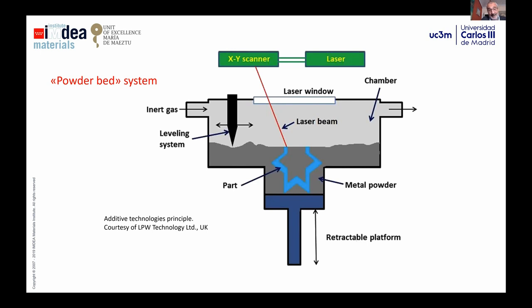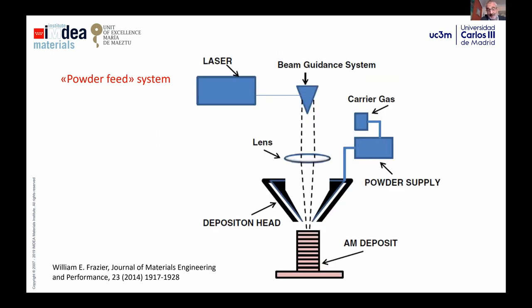We have another alternative, which is the so-called powder feed systems. The advantage of powder feed systems in this case is that we can use a mix of powders. We have different hoppers. We can feed the powders by different hoppers, and we can have different kinds of powders, and we don't need to use a fully prealloyed powder always. Of course, we can use fully prealloyed powders also. Here, we have a different concept of how we can build the part, because here we have a bottom-up method, but at the end, we have also different problems.